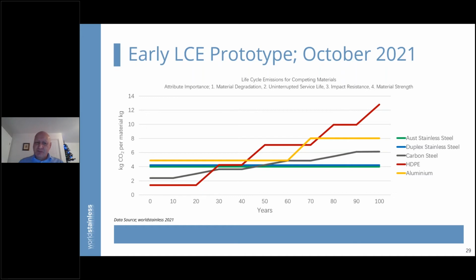But then as time progresses and interventions and partial replacements, maintenance are needed, things change. The only thing that doesn't change is the stainless. The stainless products just sit there and perform in an application that requires these sorts of attributes. So by the time you get to 30 years, you start to see a difference. The plastic has fallen out of favor on this assessment. By the time you get to 60 years, really only stainless is looking interesting.